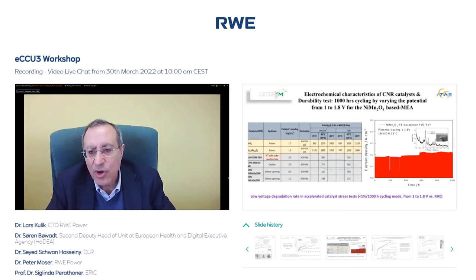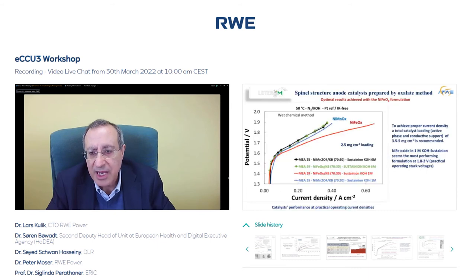So in this table, we can see at 1.8 volts versus the reversible hydrogen electrode that we have a mass activity for iridium, iridium ruthenium oxide exceeding 1,000 ampere per gram. In the case of the non-precious metal electrocatalysts, in the anionic environment, we get something like 200, 400 amperes per gram. But we have essentially very good stability for the anode electrocatalyst using some nickel manganese, nickel iron oxide with spinel structure.